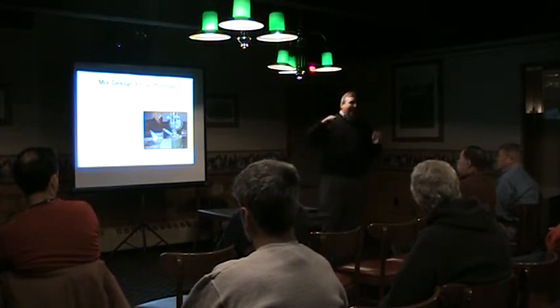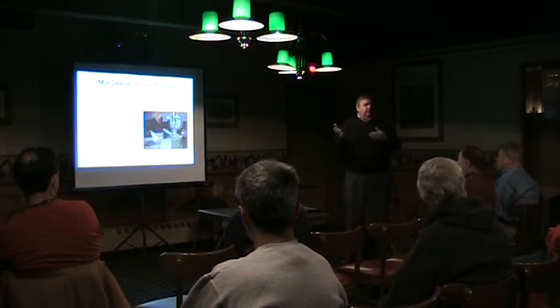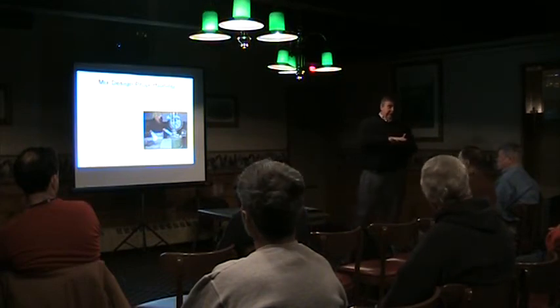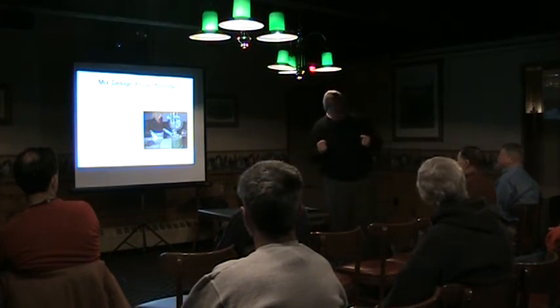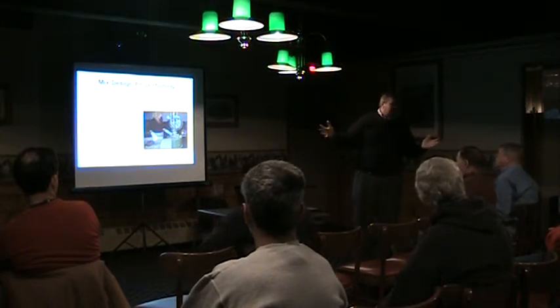We're going to try to determine how much cement we're going to mix in, so that at the end of 7 days when we do these tests, we have about 400 psi. Anywhere from 300 to 500, but we want to be in the area of 400 psi in 7 days. Now that's not exact, so we're going to use our really technical know-how, and we're going to do 3 tests. One with 3%, one with 4%, one with 5%. And whichever one comes closer, that's the one we're going to use. So that's really technical.